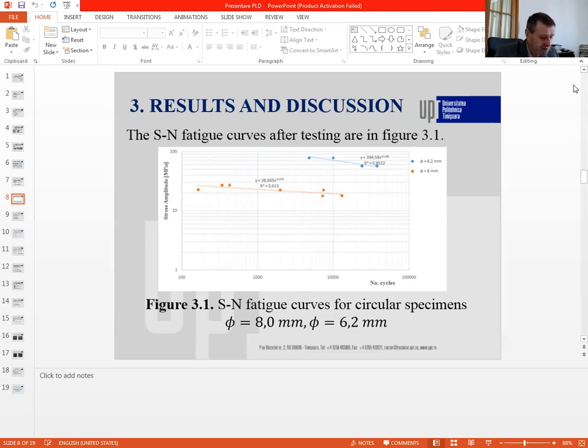The analysis of the fatigue curves in figure 3.1 shows that the fatigue strength decreases as the diameter of the test piece increases. For this reason, the dimension effect is analyzed by correlating the two experimentally obtained fatigue curves.